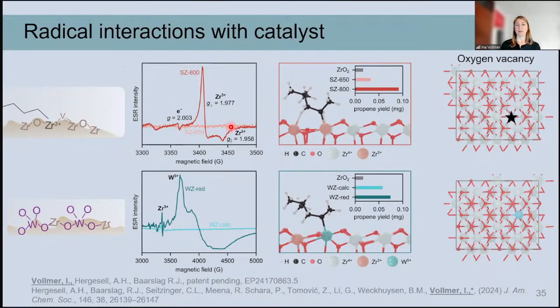But we are also thinking about some in situ experiments where we could generate the radicals somehow in the EPR, so in the electron paramagnetic resonance instrument, so that we could then see if we can generate the organic radicals and have next to it these unpaired electrons on our catalyst, and then see if these actually disappear. The signal for that disappears when the radicals then come to the catalyst material. That would of course be the ultimate proof, but so far we are mostly playing with different catalyst materials and try to draw some correlations between activity and material characterization.